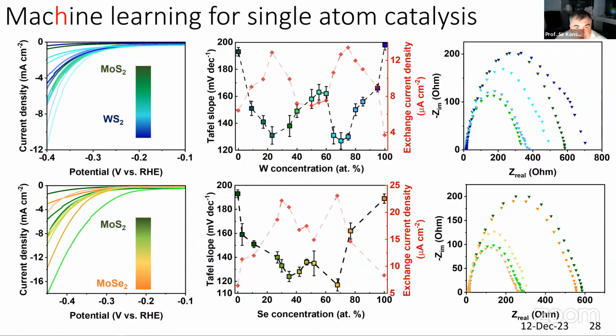And indeed, we played experimentally with two-dimensional materials as well, which are already being used for catalysis purposes. For example, MoS2, quite widely used in the petrochemical industry. And you start adding individual defects there, and you indeed can see that you get some improved catalytic properties. So probably the easiest way is to look at this central top graph, and you see that if you start with pure, so zero concentration of tungsten means pure MoS2, you add a little bit of tungsten inside and your Tafel slope goes down quite significantly.